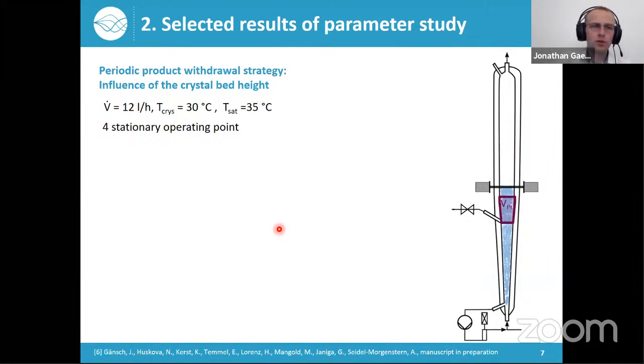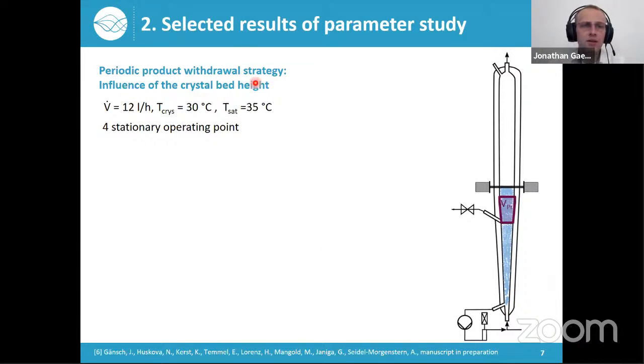Regarding the periodic product withdrawal strategy, here we could observe that the height of the crystal bed has an unexpectedly strong influence on the process performance. So what did we do? Starting from our reference strategy, we changed the position of these photosensors.